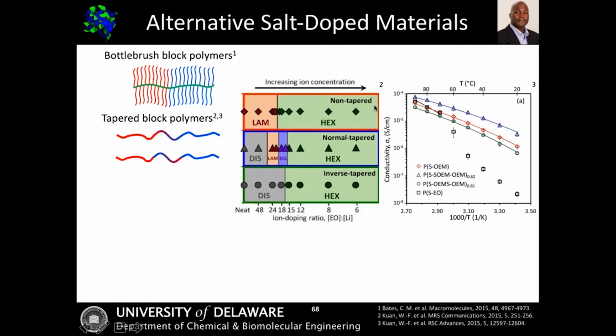By doing that, what you can see is just some of the differences that you can get in phase behavior. So for example, the non-tapered or traditional block copolymer forms things like lamellae and hexagonally packed cylinders, whereas by putting in different types of tapers, you can see two key features. One of the first things is that as a function of salt loading, I see that I actually get disordered phases at lower salt loadings, but as I increase salt loading, going from left to right, that I get a variety of nanostructures, including things like this triply periodic double gyroid structure.